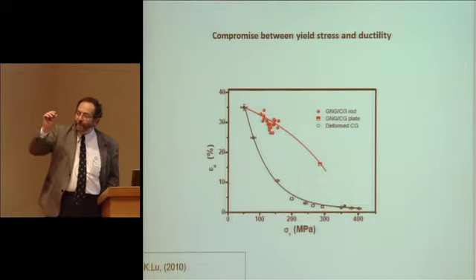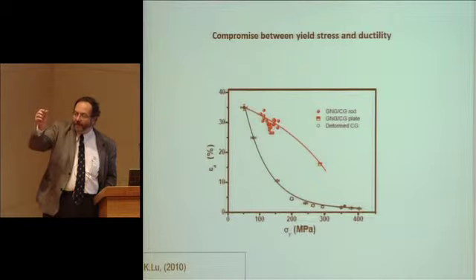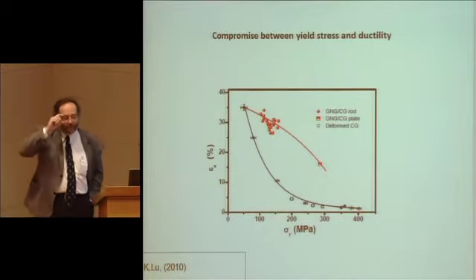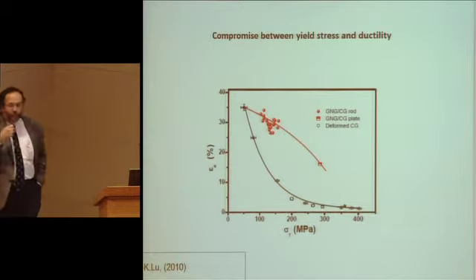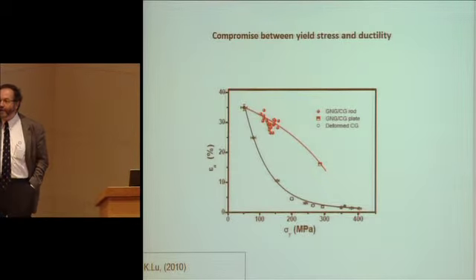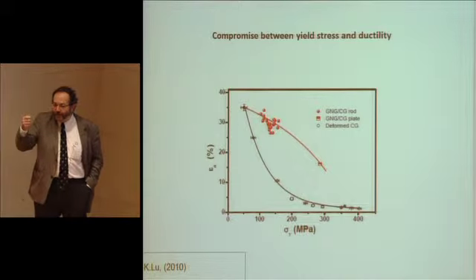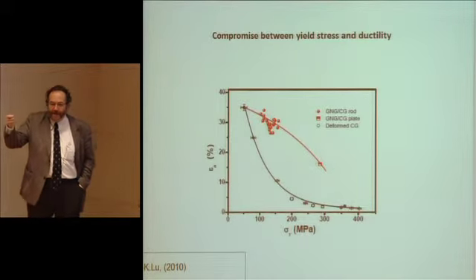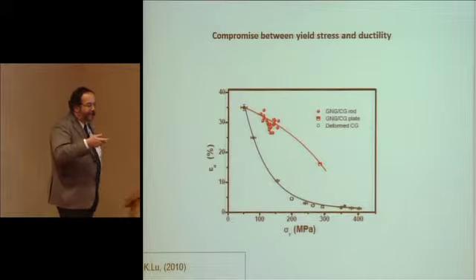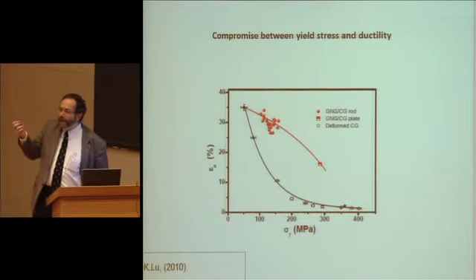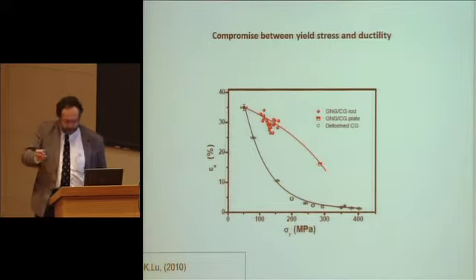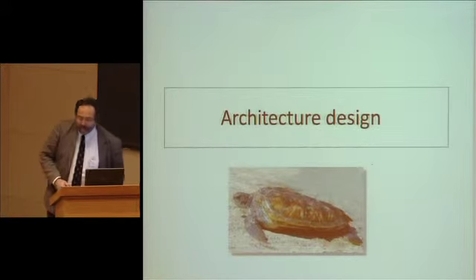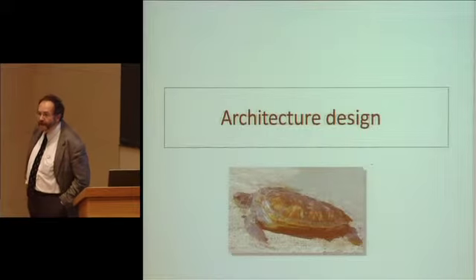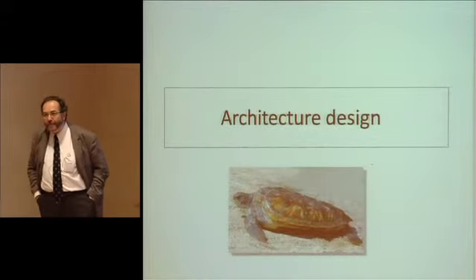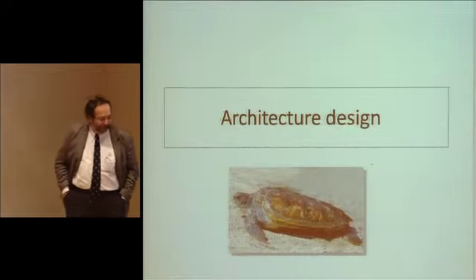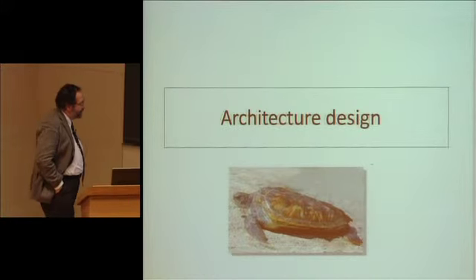And in red, you have the same material where a surface layer has been applied, where this kind of hyper-blasting, and it's compressed, and therefore that's going to prevent crack propagation, and it's kind enough to considerably increase the rate of work hardening. When it deforms, it finds it more difficult. So again, a case in which you're trying to play not on the constitution of the material, but on a gradient of microstructures. So you have seen another strategy, which is that of architecture design, when you try to have an influence on the forms, on the shapes.